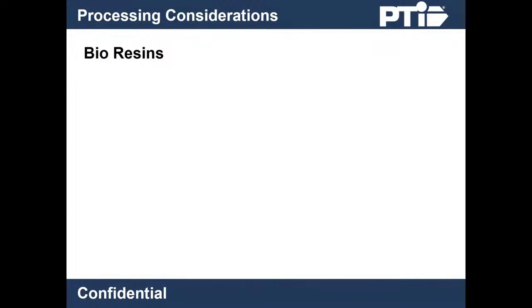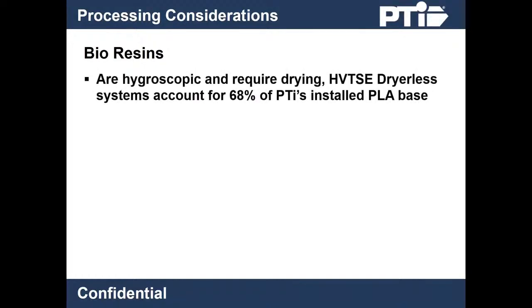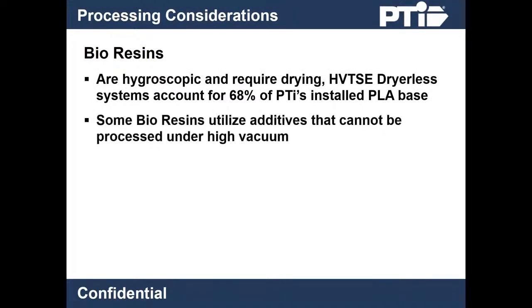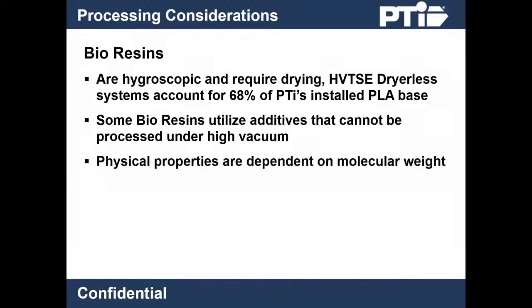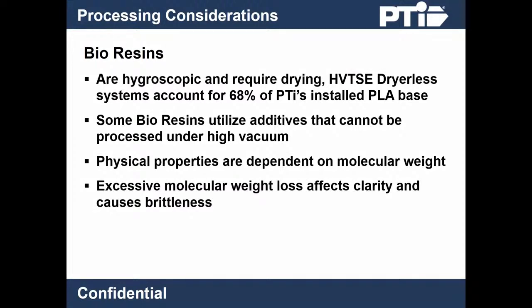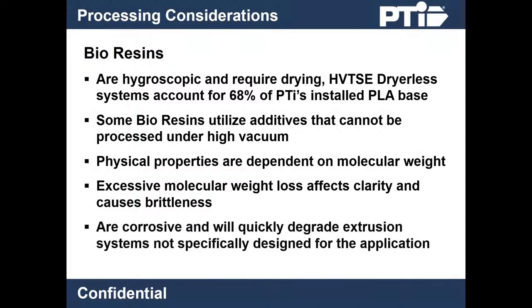Other considerations when processing bioresins include, one, that bioresins are hygroscopic and require drying. HVTSE dryerless systems account for 68% of PTI's installed PLA base. However, some bioresins utilize additives that cannot be processed under high vacuum. These require single screw extruders. The physical properties are dependent upon molecular weight. Excessive molecular weight loss affects clarity and causes brittleness. And finally, that bioresins are corrosive and will quickly degrade extrusion systems that aren't specifically designed for the application.